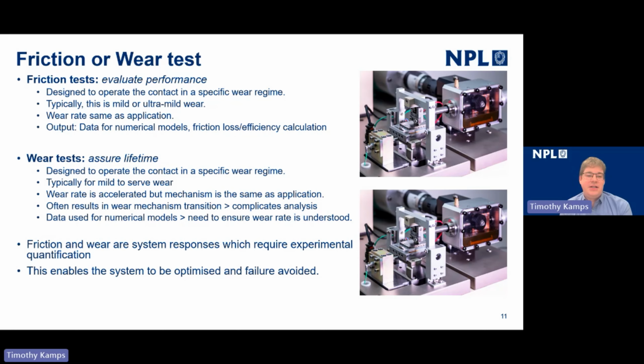And this is quite a challenging experiment to do because there can be cumulative effects, heat dissipation in the contact that can have quite a long time base to them. And so sometimes unexpected failures occur due to wear tests that have been artificially accelerated above the threshold at which they exhibit the same failure mode.